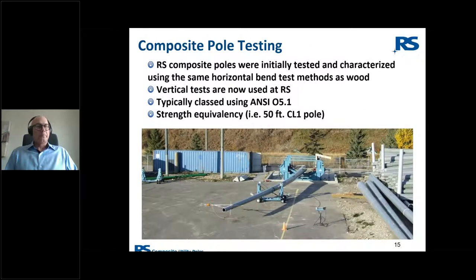Okay, so composite pole testing. Here at RS, our poles were initially tested and characterized using the same horizontal bend test methods as wood. So that would be per ASTM D1036. At RS, we now use vertical test methods. The reason we do that is for P delta performance capturing.